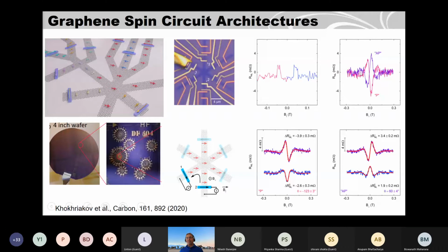So this is the asymmetric signal for the parallel one, and this is for the anti-parallel one. And from this signal, you can find out the components for the symmetric and anti-symmetric parts. Okay, and these are for different angles, 120 degrees around and 60 degrees.